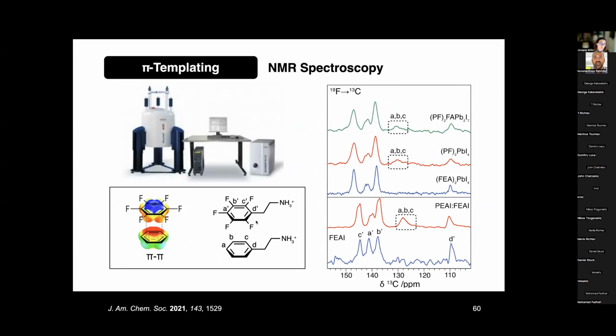In this case, by relying on the fluorine to carbon cross-polarization measurements that once more exploit these through-space exchanges in magnetization through dipole-dipole interactions that are effective within ranges of up to about 1 nanometer, which can happen due to nanoscale proximity, such as by pi-pi interactions, resulting in the fluorine to carbon cross-polarization NMR spectra in the appearance of these additional signals highlighted here in both the mixtures of neat spacers as well as the corresponding layered perovskite architectures, suggesting their presence in nanoscale proximity as desired.